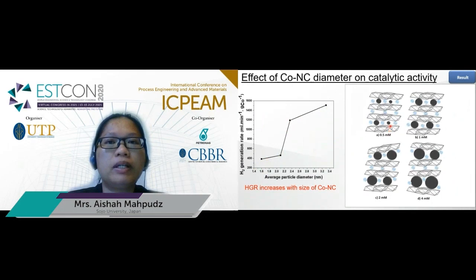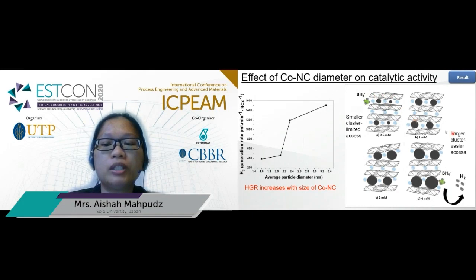And this can be explained by the accessibility of the active cobalt species in the interlayer of LDH. Compared to the bigger particles, smaller cobalt nanoclusters have limited access of the borohydride ion to the active cobalt surface because of the smaller interlamellar space. However, the bigger particle has a larger interlamellar space, which gives easy access for the borohydride ion to reach the surface of the active catalyst.